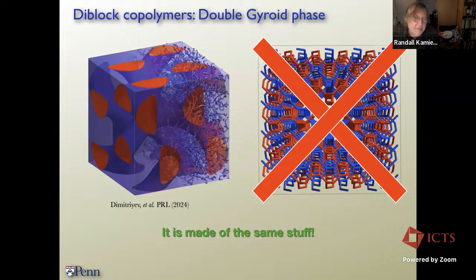Okay, experimentally it has been seen. Experimentally it's very difficult when you look at pictures to distinguish, say, the gyroid from the diamond phase, but careful experiment has shown it's the gyroid phase. And you can do other things like neutron scattering. You can do this in Fourier space too by doing neutron scattering and so forth.